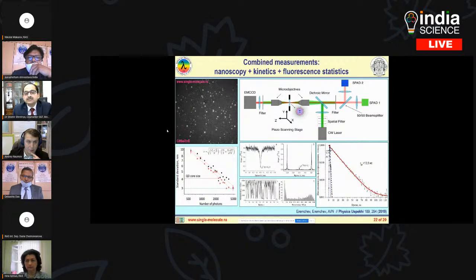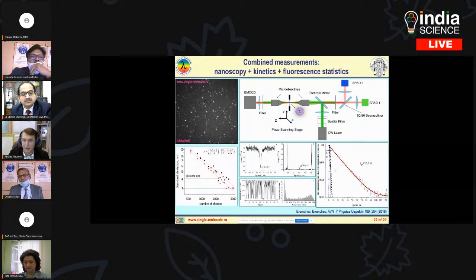You see, this is a picture from our recent measurements. We excite quantum dots, which are located on a glass substrate, with a continuous wave laser. And you see the effect of so-called blinking behavior. You see that these bright single quantum dots stochastically jump between bright and dark states. And of course, if we try to use such quantum dots for any applications, we should understand the nature of this very intriguing behavior. At the same time, we can reconstruct the position of each quantum dot with huge accuracy, up to a few nanometers. The same idea as previously with single molecules. And we can measure some temporal behavior and the relaxation behavior and so on.